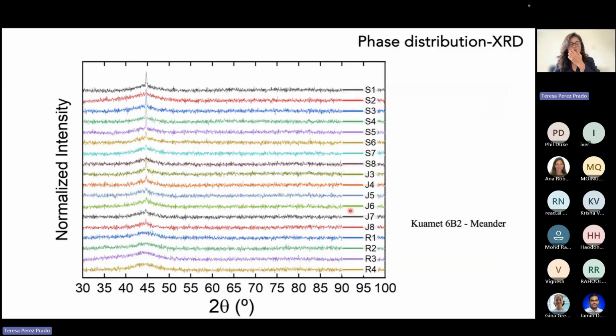And what I'm showing you here is more an overall view of this whole stack of XRD patterns. These S samples are the ones where we fix a time delay of 50 milliseconds and change scan speed and laser power. This J series are the samples with a fixed set of power and scan speed, but increasing time delays from like 50 to 200. And these R values are samples produced using a time delay of 50, but double scan.